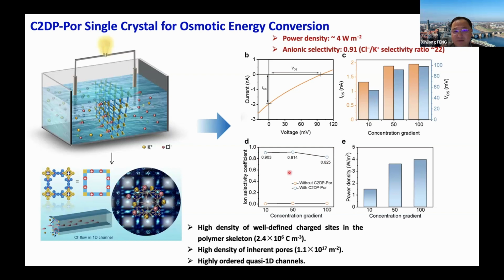And they have very good selectivity, with this selective charge for the chloride anion at 90%, and the potassium selectivity can reach more than 20 times. This will end up with a very reasonable power density for the anion, especially for chloride anion penetration, to make this device workable for these materials.